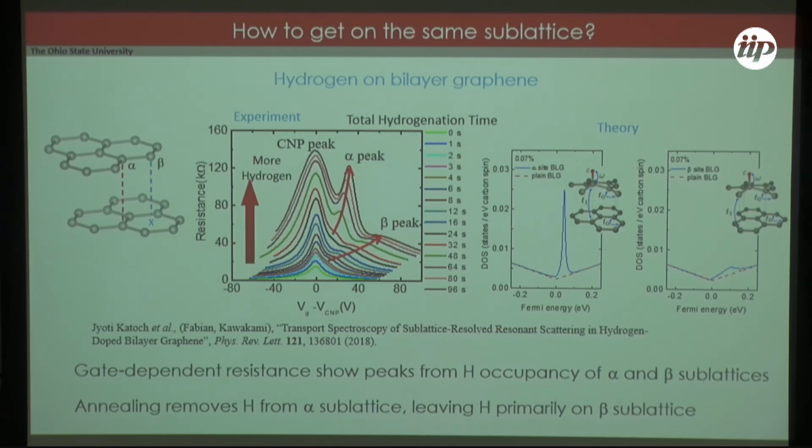Actually, I just remember one paper we published where we found an anomalous suppression of quantum interference when you have long-range ferromagnetic ordering. That is, all these hydrogen impurities are populating one of the sublattice. So for some reason, the other sublattice that is preserved is offering a channel for ballistic transport or whatever you like, and there is a signature that we have predicted. So that's what my question was related to, but I just remembered now. I see.